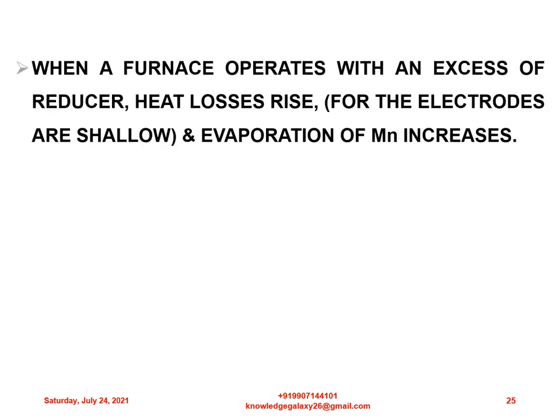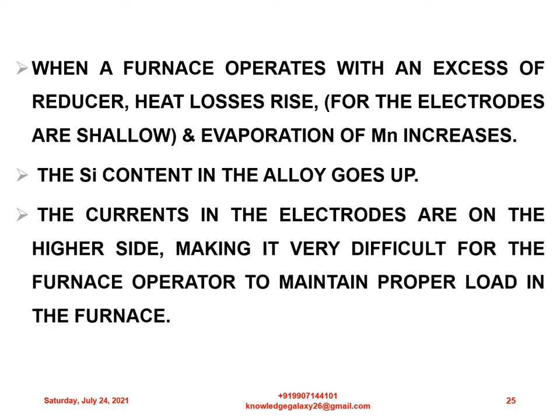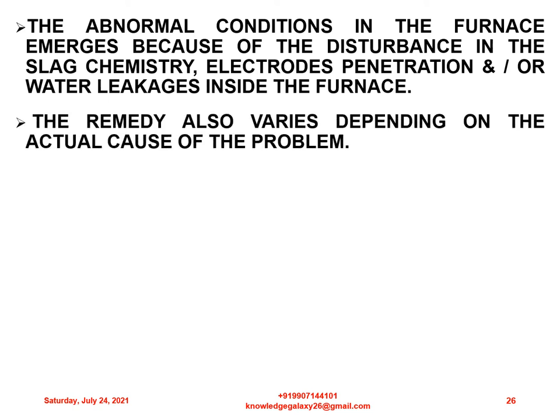When a furnace operates with an excess of reducers, heat losses rise, for the electrodes are shallow, and evaporation of manganese increases. The silicon content in the alloy goes up. The currents in the electrodes are on the higher side, making it very difficult for the furnace operator to maintain proper load in the furnace. The abnormal conditions in the furnace emerge because of disturbance in the slag chemistry, electrode penetration, and/or water leakages inside the furnace. The remedy also varies depending on the actual cause of the problem.